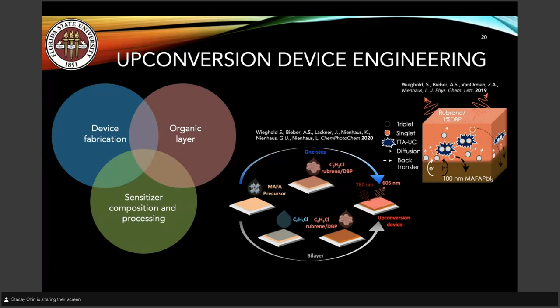More recently, we've actually been able to show that you can mix the rubrene directly into the anti-solvent. So this is a so-called one-step device fabrication, which may lead towards more facile applications in actual commercial devices. We've spent some time looking at the organic layer. So in particular, we've seen that there's different rates of upconversion, but mostly there's strong back transfer. So these are still problems that we're looking at. Next slide, please.